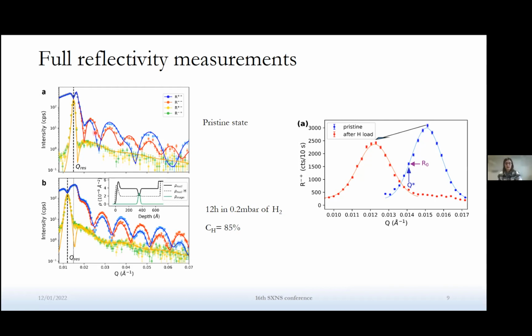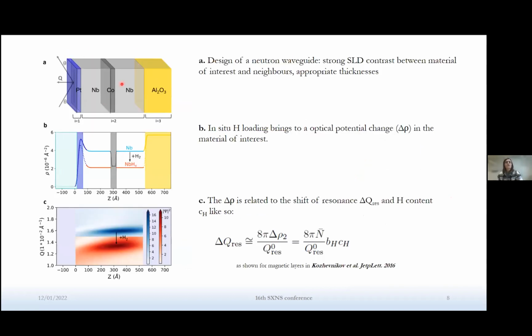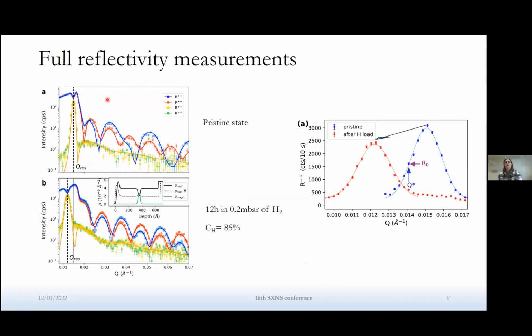As I forgot to mention, in between our niobium layer, we had this thin cobalt, which is there just to have a non-collinear magnetization, which we use as a secondary channel to detect this resonance. And you can see here a zoom of this resonance peak in the pristine sample, and at the end of the absorption, there is this shift in Q as expected.